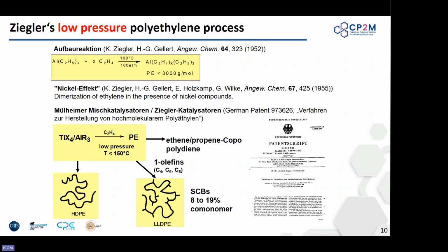And they discovered something that was coined the nickel effect. Okay, so if you have a little bit of nickel residues in your batch reactor, you will have an issue. You will not be able to fully oligomerize. You will have a beta hydride reaction with this nickel that will only allow you to go from ethylene to butene. Okay, that's barely an oligomerization. It's more dimerization. But when they realized that, they thought, oh, that means that if I add a little bit of a metal, maybe I can tune that. Maybe I can go longer. Maybe I can be very selective for butene or whatever.